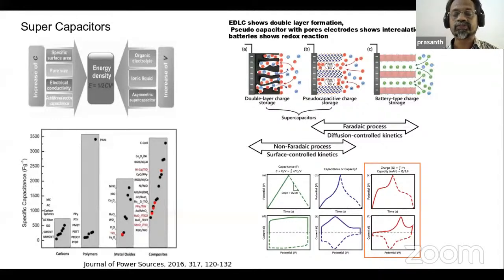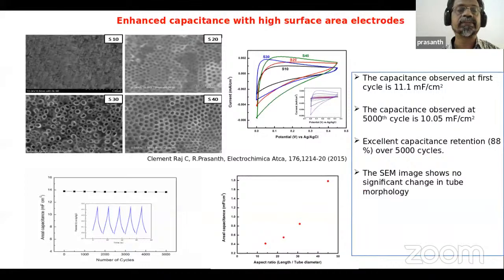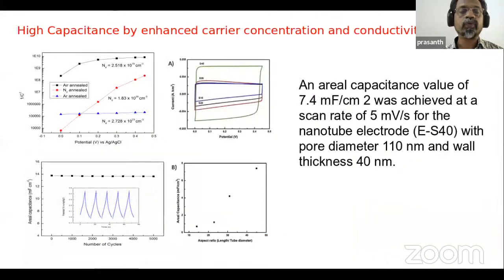So when you are doing this characterization, the typical characterization, as compared to a battery or a supercapacitor, will show a square type of current-potential characteristic, the CV characteristic you can say. In that case, what we can see with a single titanium dioxide tube with an electrolyte like HCl or sodium chloride, you can use different electrolyte systems. We worked this out. You can see there is a reasonable capacitance, but it is not a commercially competitive value, and it's showing good stability of electrical storage.